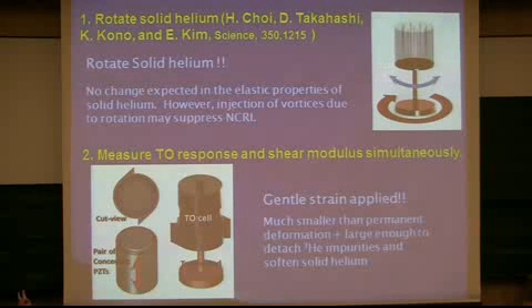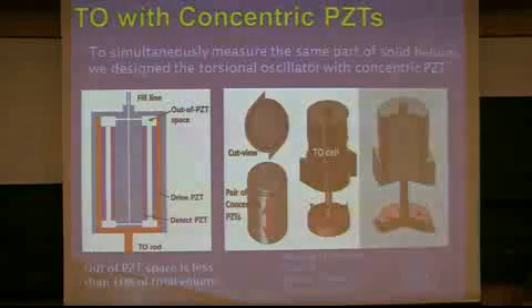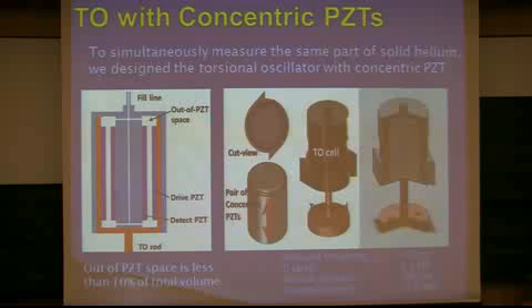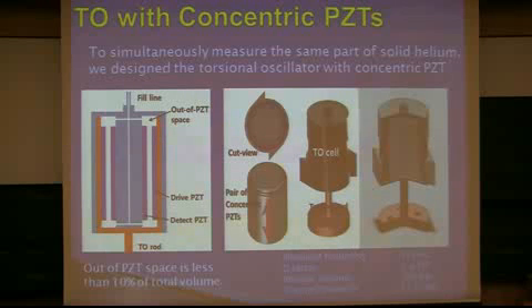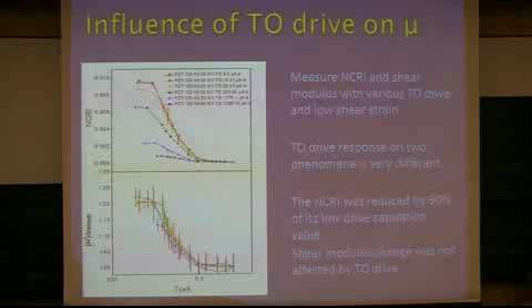I told you I did two experiments. As I told you, I'm a really hardworking experimentalist. I'm not satisfied with the first experiment. That's why I did a second experiment. What I have done is I simultaneously measured the shear modulus and the non-classical rotational inertia, the torsional oscillator response, at the same time. So this is the torsion cell. Here, instead of planar PZT, I use the concentric PZT. So I measure the solid helium in the annular channel. And also at the same time, I can do the torsional oscillator experiment. And this is the result.